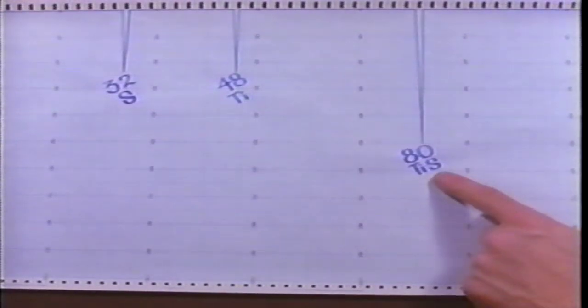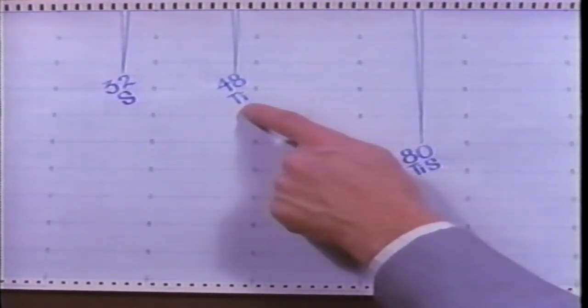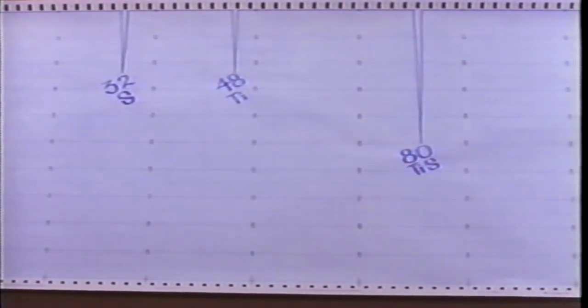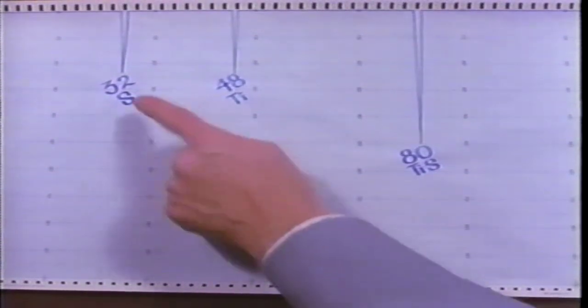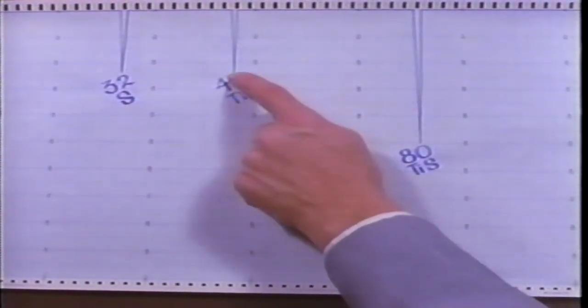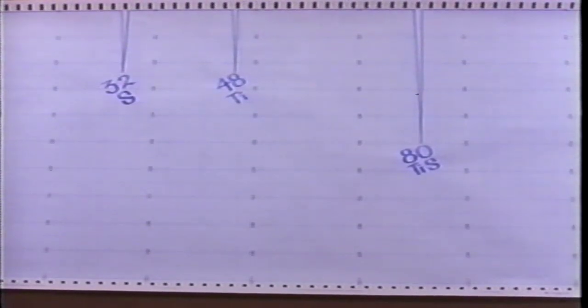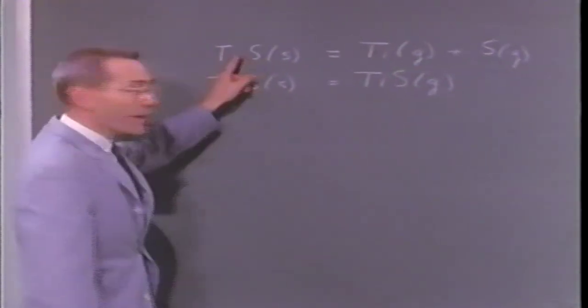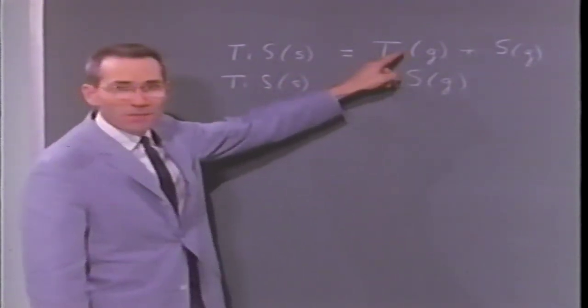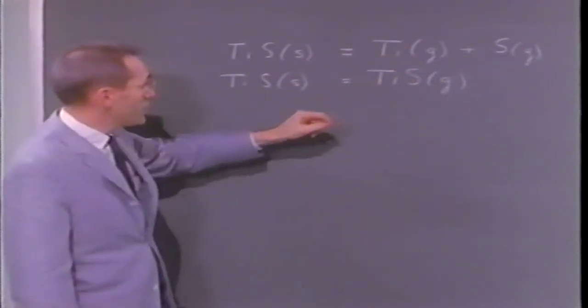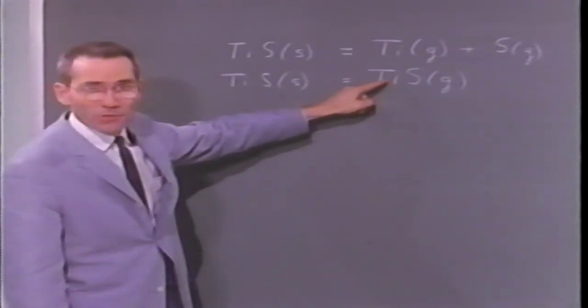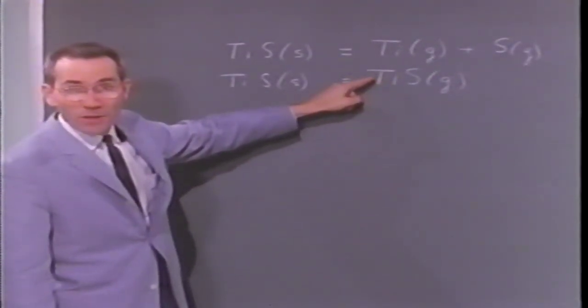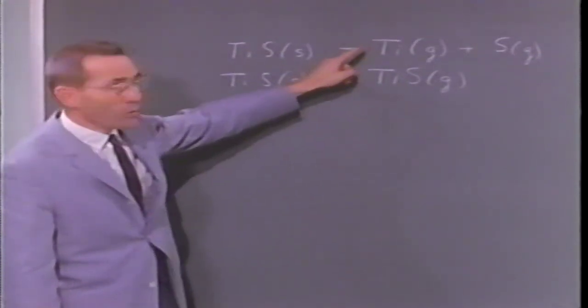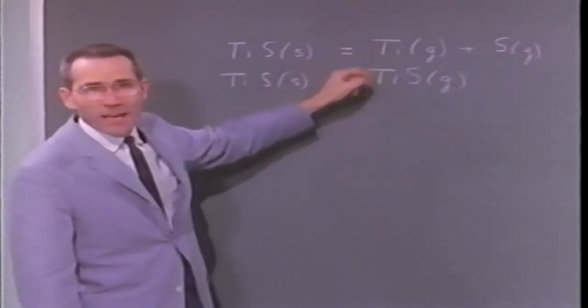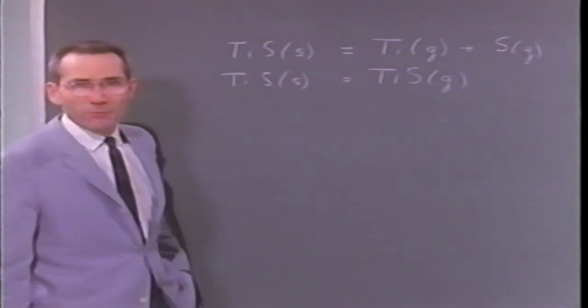The relative peak heights, and hence the pressures of TiS and titanium, are very nearly in the ratio 2 to 1, actually 2.10 with an experimental uncertainty. The pressure of sulfur and the pressure of titanium are the same. Well, we've answered one question. TiS vaporizes to give titanium atoms and sulfur atoms. Also, it vaporizes to form TiS molecules. Now, we also saw that the pressure of TiS molecules is 2.1 times the pressure of titanium atoms at this temperature, which you remember is 1805 degrees Kelvin.